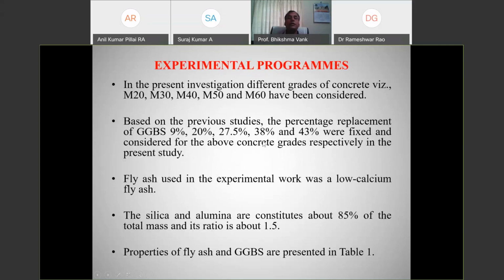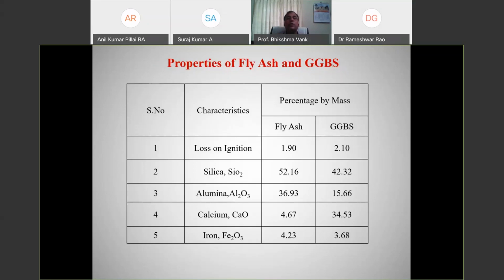As I told you, I can show you this research for M20 to M60 grade concrete with replacement of GGBS from 9% to 43% after several trial mixes. We have obtained these values. The properties of the fly ash and GGBS are like this. We have investigated the fly ash material and GGBS.